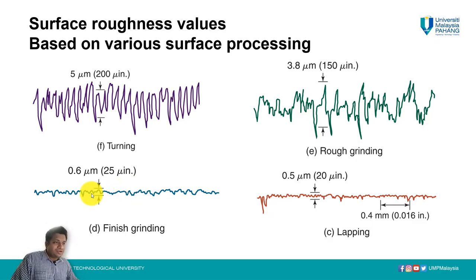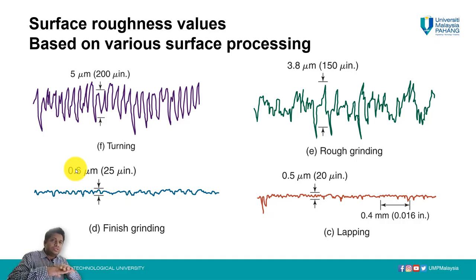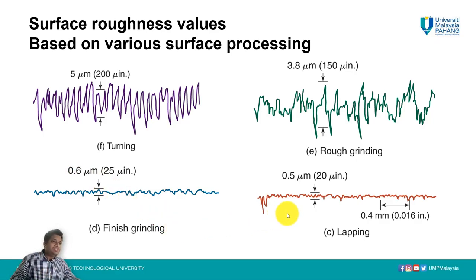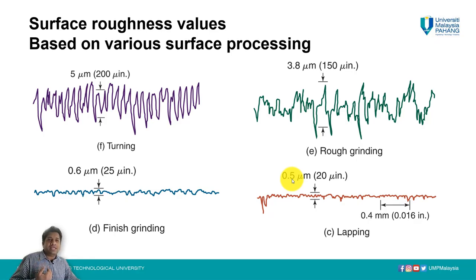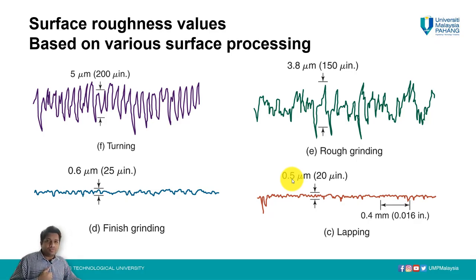For finish grinding you can get less than 1 micron, moving towards a smoother surface. In polishing processes — like those done on automobile metal surfaces — you can further reduce roughness. In lapping you can reduce surface roughness to about 0.5 microns. Using nano-diamond grinding fluid and polishing fluid with alumina of 3, 6, and 1 micron grades, roughness can be significantly reduced.